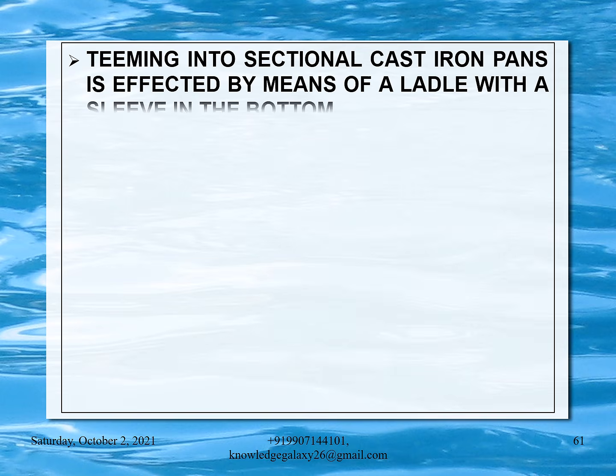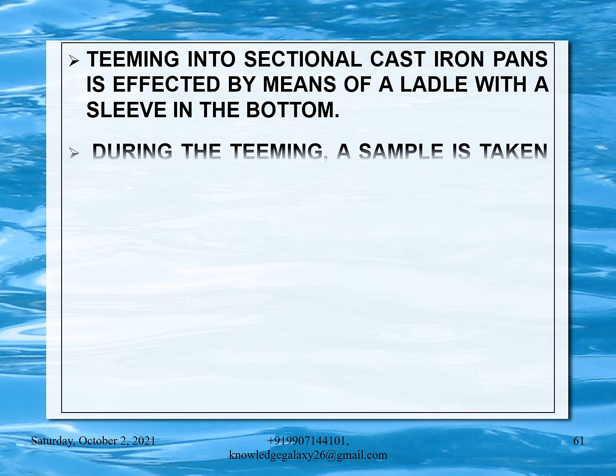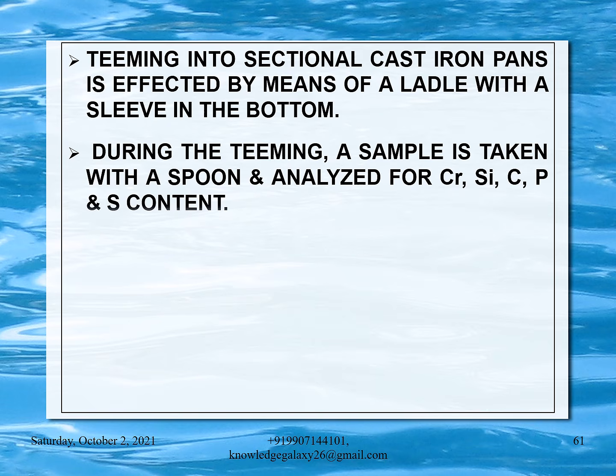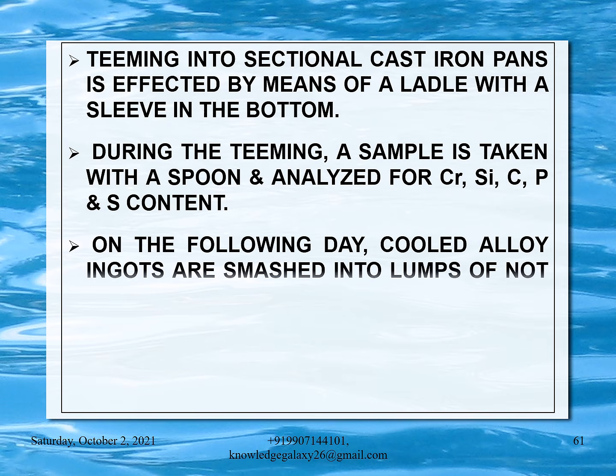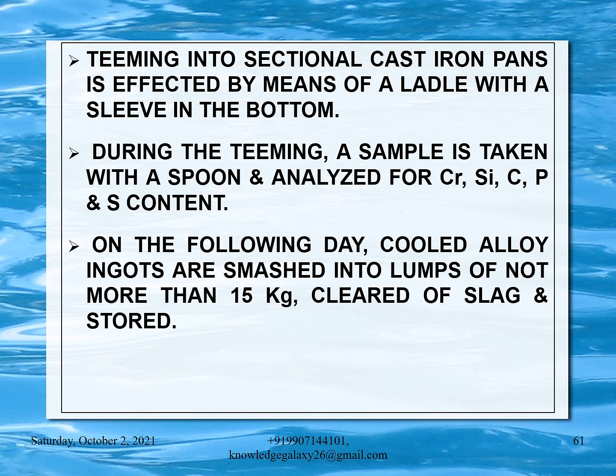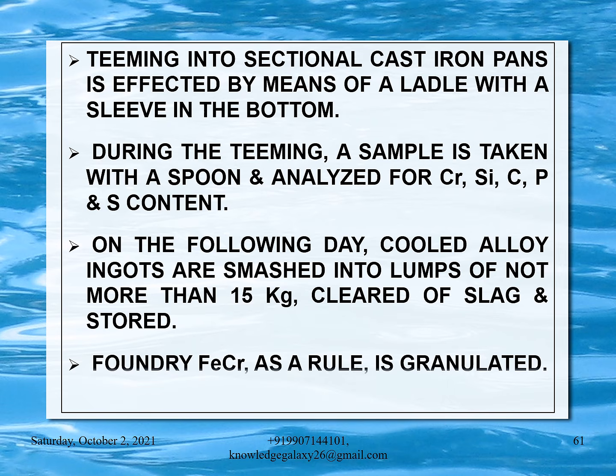Teeming into sectional cast iron pans is effected by means of a ladle with a sleeve in the bottom. During the teeming, a sample is taken with a spoon and analyzed for chromium, silicon, carbon, phosphorus and sulfur content. On the following day, cooled alloy ingots are smashed into lumps of not more than 15 kg, cleared of slag and stored. Foundry ferrochrome as a rule is granulated.